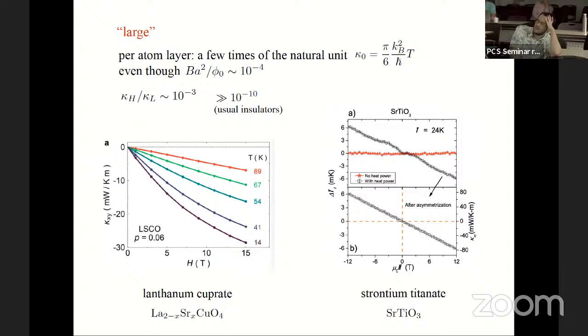Another reason we think it's large: first, it's order 1 in the natural unit, but the magnetic field is 10 to the minus 4. So the effect seems to be very large, even though it's linear in the magnetic field. And the second way to think that it is large is that the Hall angle, kappa H over kappa L, is 10 to the minus 3. If you take a simple insulator, for example, salt that you eat, sodium chloride, it has some ions, right? The ions have some charge. So when a phonon moves an ion, maybe there can be some coupling to the magnetic field. And you find the Hall angle is 10 to the minus 10. In a usual insulator, it's 10 to the minus 10. But this ratio here is 10 to the minus 3. It's way larger than the usual.